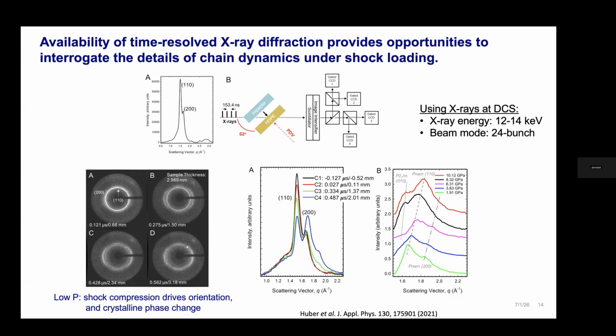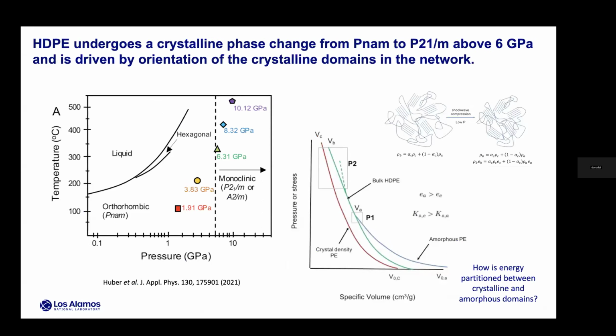That's, I believe, some of the first measurements of their kind to be able to observe these phase transitions in the crystalline domains within the polymers, especially because they're low Z materials, and those crystalline domains are only a portion of the structure. And I will say, I think the only way that this has been possible is by using third generation and now fourth generation light sources.